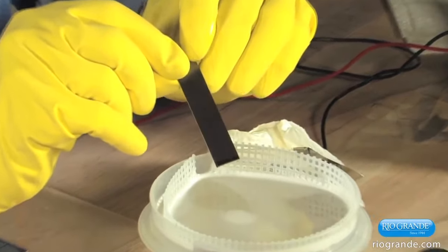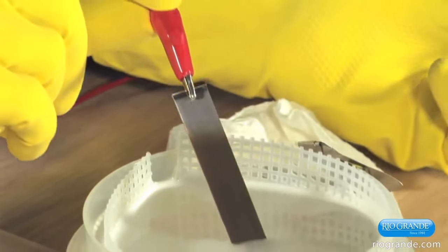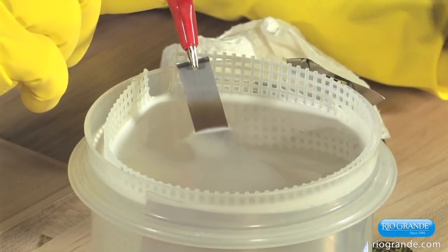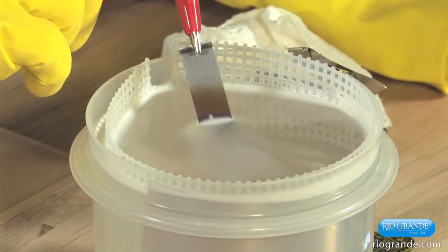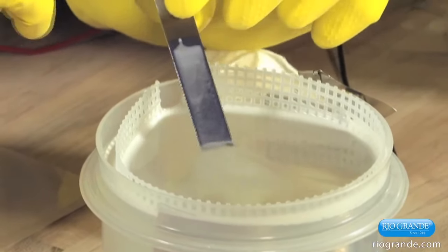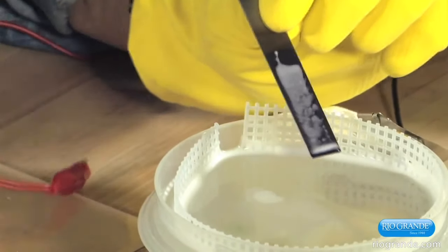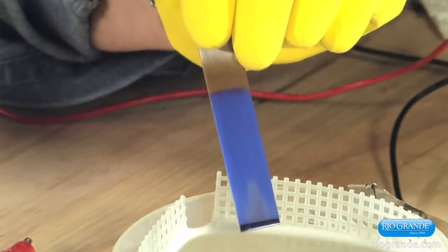We have a nice brown. I'm going to hook it back up, submerge it in the bath, not quite as deep, and I'm going to turn it up to 22. Now we have a second color. We have a darker blue.